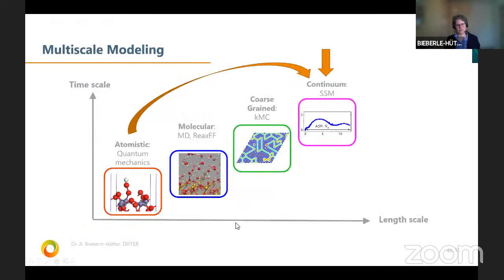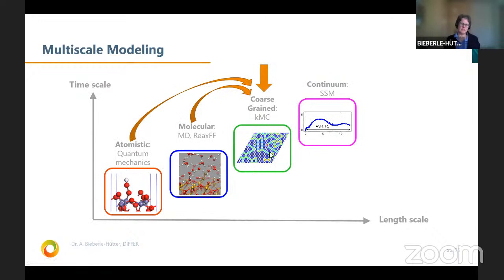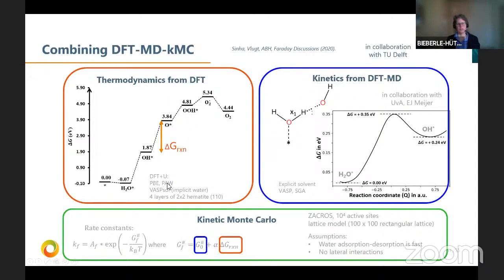I'm almost at the end of my presentation, but I would like to use the last few minutes also to show you something we also did in addition to this. What I showed you now, we use DFT and then do a kind of continuum modeling. What we have also done with a postdoc recently is that we combine DFT with MD and kinetic Monte Carlo. And this is shown here. So actually the student did DFT with implicit water, and then calculated the kinetics of single steps, determined the activation energy for this process here, and then used the kinetic Monte Carlo approach to actually simulate